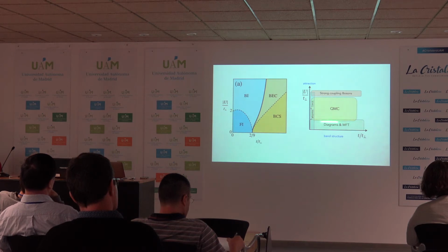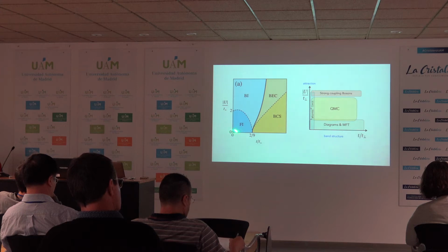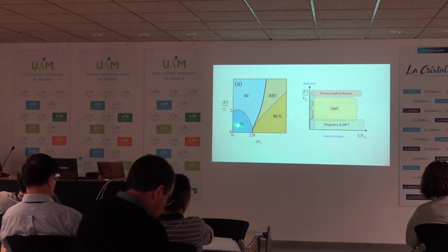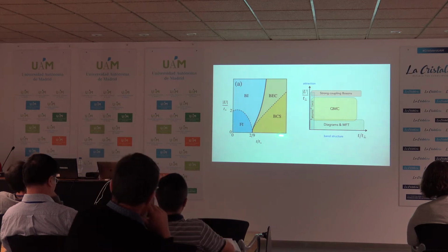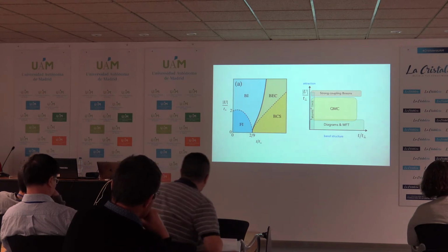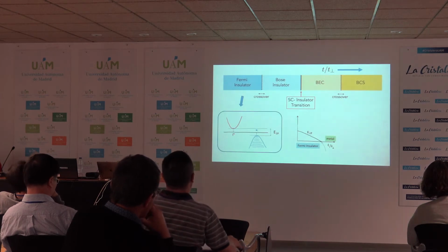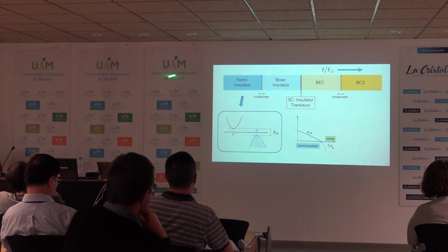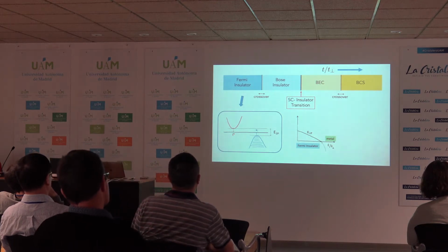But that is going to be the fate of this Fermi band insulator at, let's say, a fixed value of the attraction as we turn on the hopping within the layer. Okay, and on the other hand, if you sit at a particular value of the hopping and just increase the attraction, then depending on where you are, you need not go through all the phases. The Fermi insulator could just become a Bose insulator and it could remain insulating. So the behavior is very different depending on how you tune through this. Okay, so what exactly are these phases? I'm going to show you that through a couple of sketches and then some actual results.